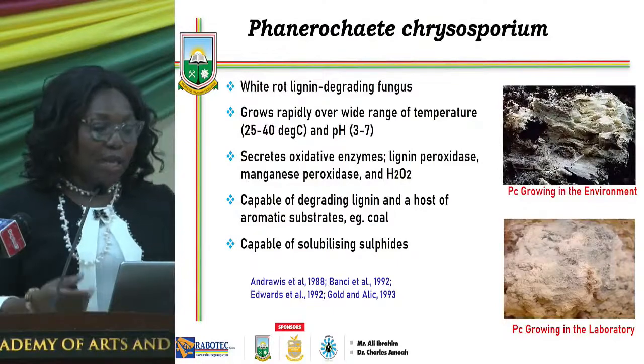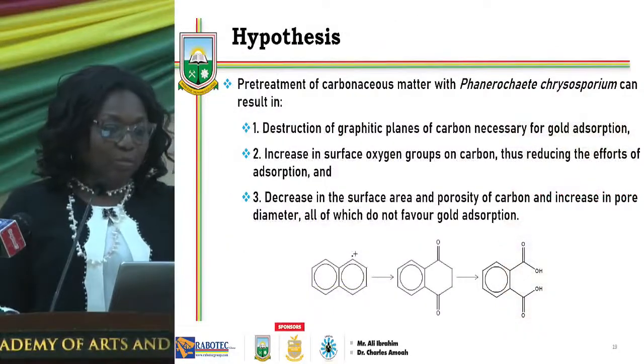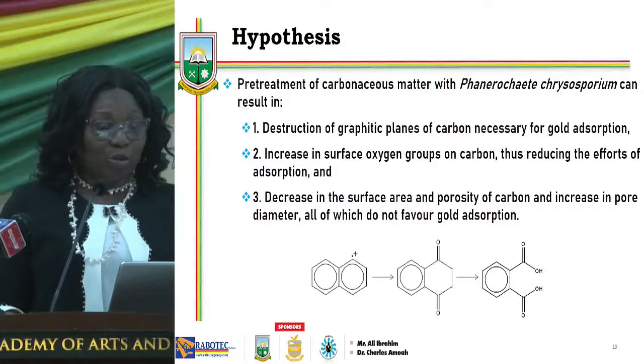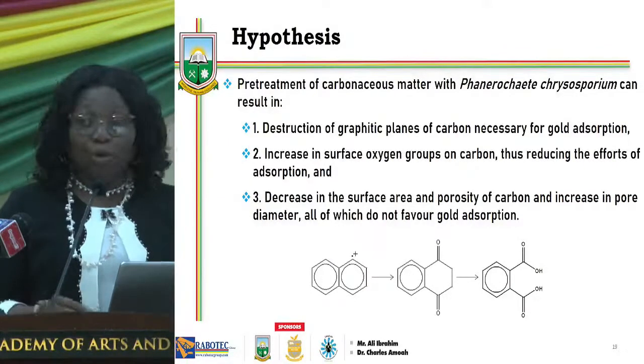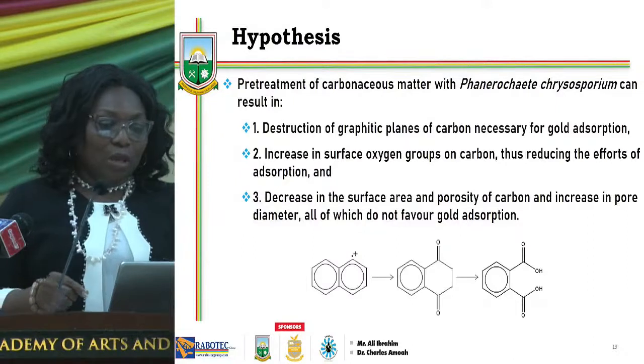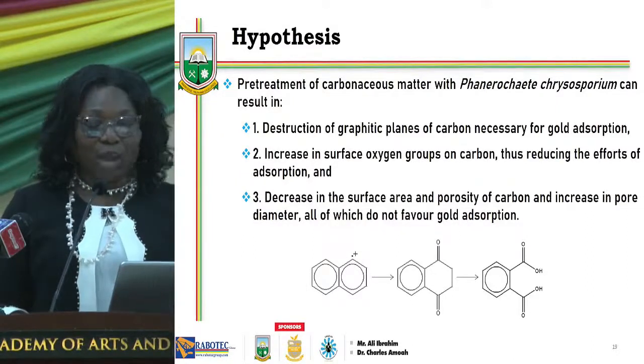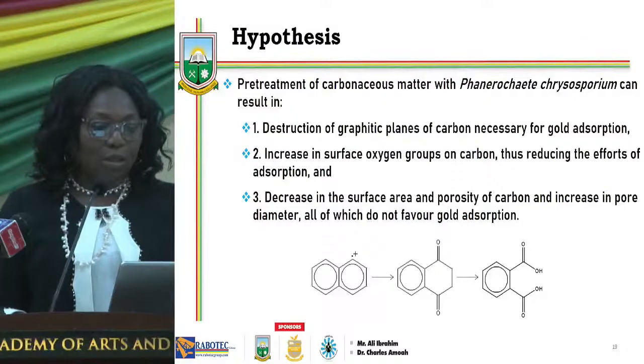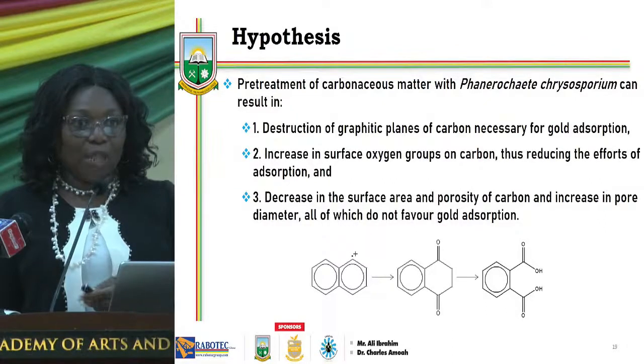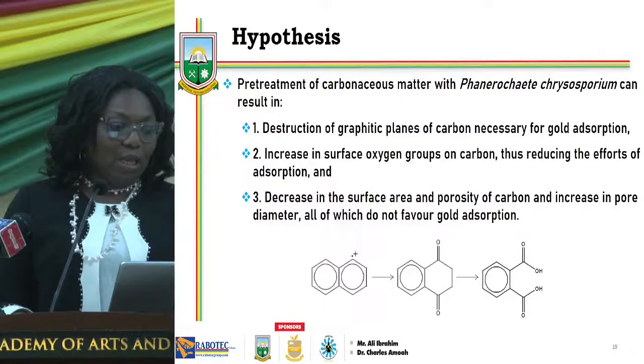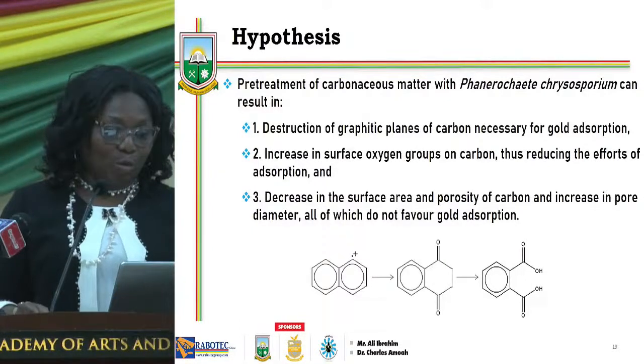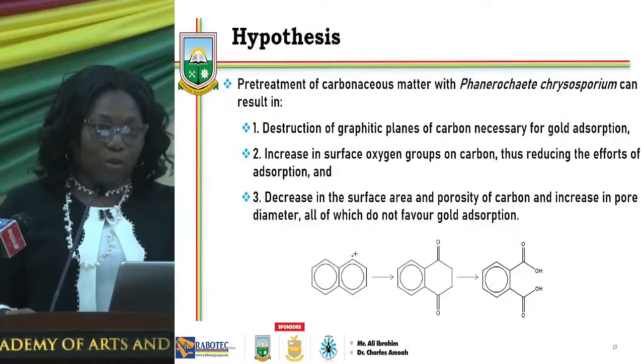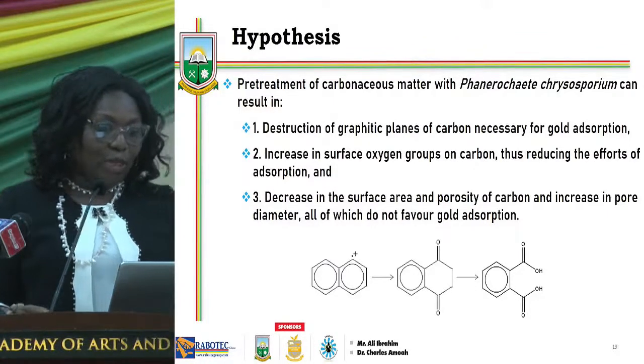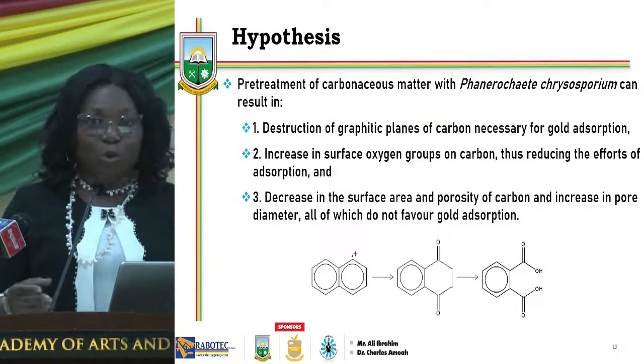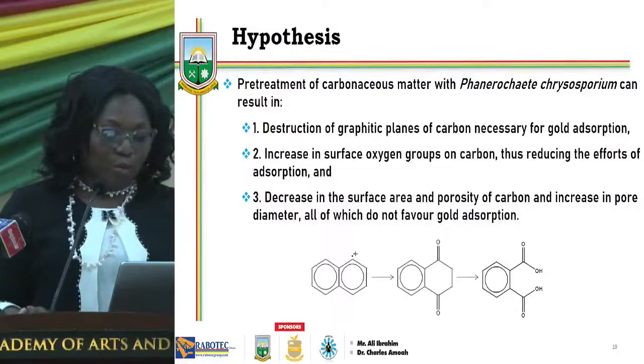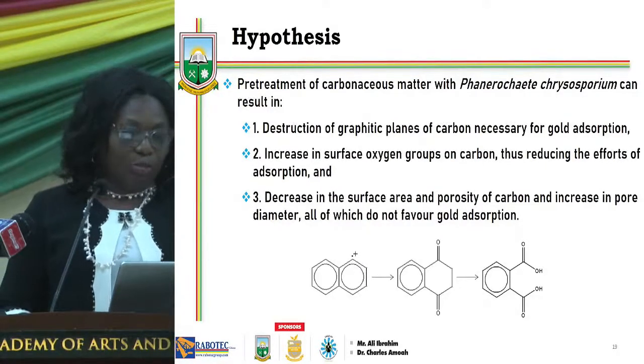Using that, I came up with the hypothesis that pretreatment of carbonaceous matter using Phanerochaete chrysosporium can result in destruction of graphitic planes that are necessary for gold adsorption. That an increase in surface oxygen groups on carbon will not help with gold adsorption. And that a decrease in the surface area and porosity of the carbon will also not help with gold adsorption.